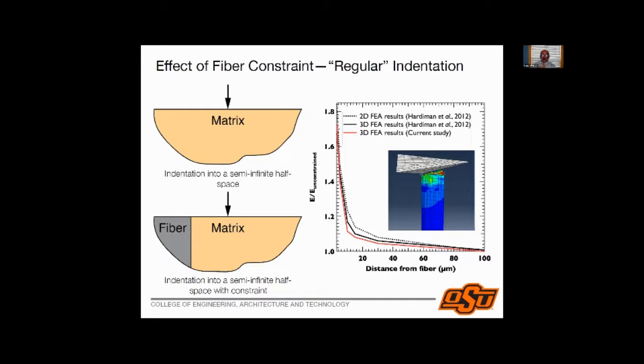Unfortunately, the problem we have over here is that I am carrying out indentation right next to a fiber. The elastic modulus of a carbon fiber is about 300 GPa. The elastic modulus of a matrix is about 3 GPa. So the fiber is two orders of magnitude higher in stiffness than the matrix. So as far as the matrix is concerned, this is rigid. The fiber is not going to go anywhere.